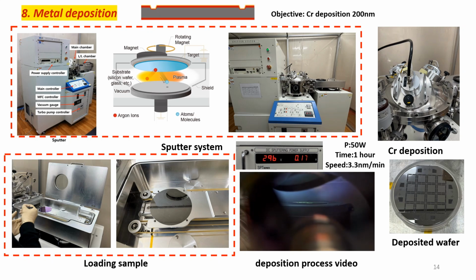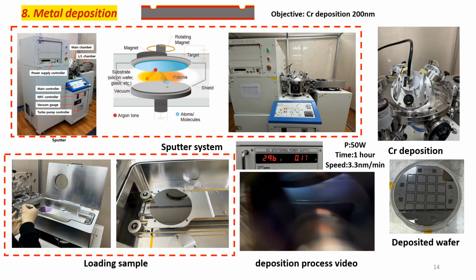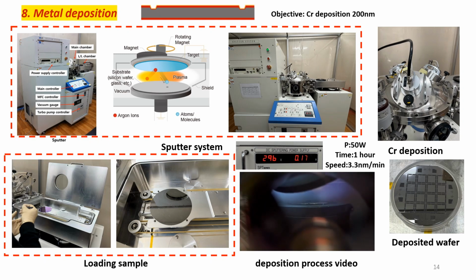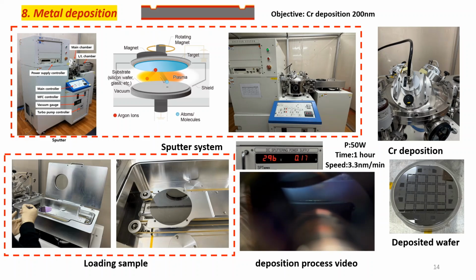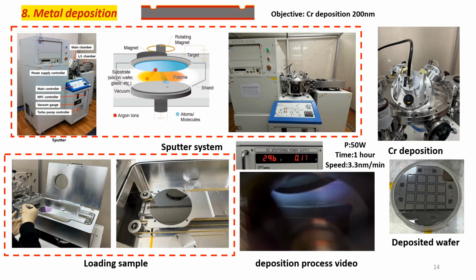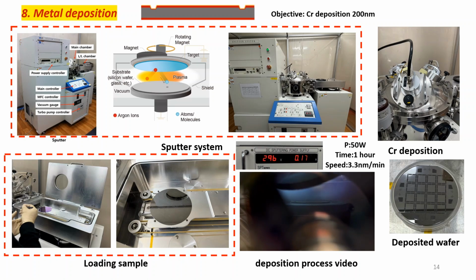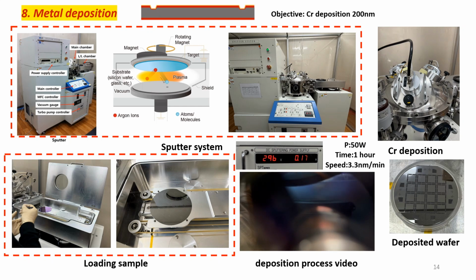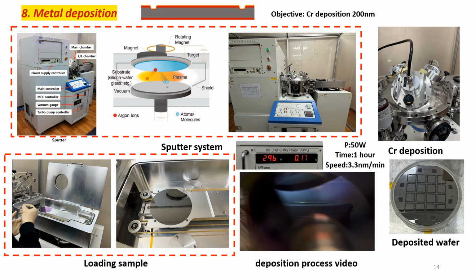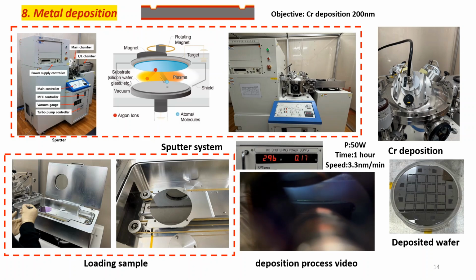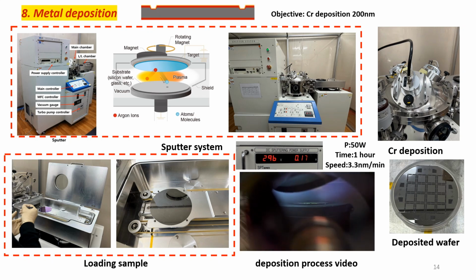In order to make a metal pattern, we use a sputter system to deposit metal, mainly through the collision between atoms. Metal atoms will deposit on the wafer surface. We use chromium for deposition. After loading the wafer, in order to achieve a 200 nanometer thickness deposition, we set the power to 50 watts and the deposition time to 1 hour. The video shows the deposition process. Finally, we obtain the wafer after deposition as shown in the figure, and the color is gray.